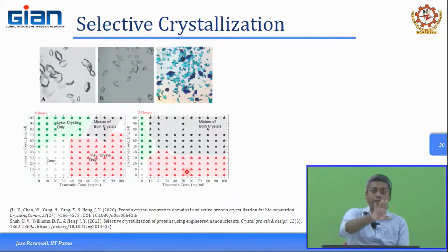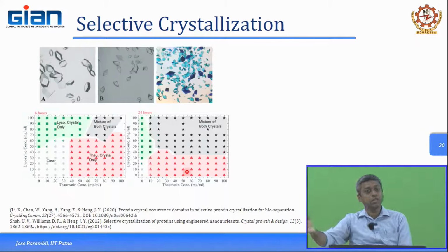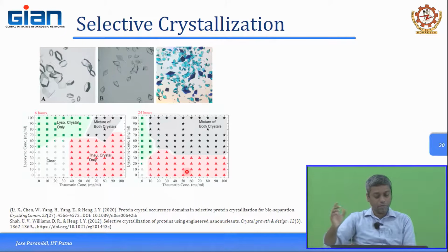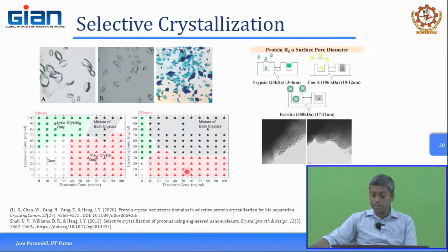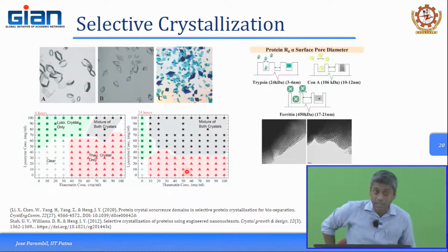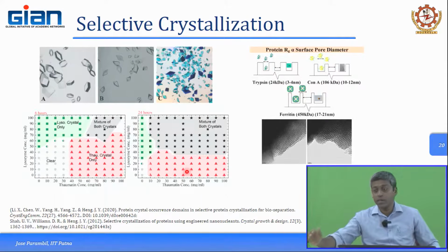So, the starting mixture is the same, out of it you are selectively crystallizing one protein and removing the other. So, let us say after the first crystallization you remove as much lysozyme as there is, and in the next stage of crystallization you can crystallize and remove as much thaumatin as there is. So, you can manipulate or optimize the process conditions in such a way that you can crystallize one after the other. Another approach which has been reported is using templates, in the sense that proteins, as we discussed earlier, are notoriously difficult to nucleate. So, you can support or enhance the nucleation by providing external heterogeneous templates.